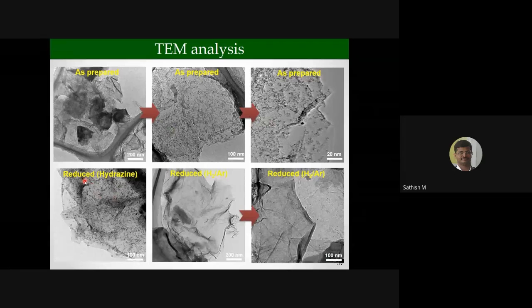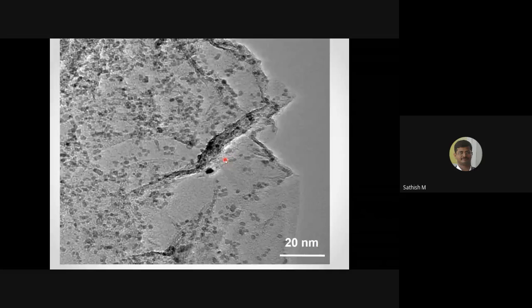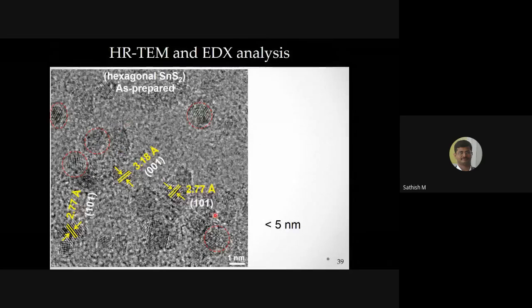So this is a reduced graphene sheet. You could see reduction through the hydrazine method, and in this case the hydrogen and argon mixture. This is gas phase reduction, and this is solution phase reduction. You could see in the case of gas phase reduction, only a few materials are present, while on the other side it is uniformly dispersed. When you enlarge the solution-based material to high magnification, you could see small crystals decorated. When you go to really high magnification of 1 nanometer, you could see the crystalline nature of this tin sulfide.